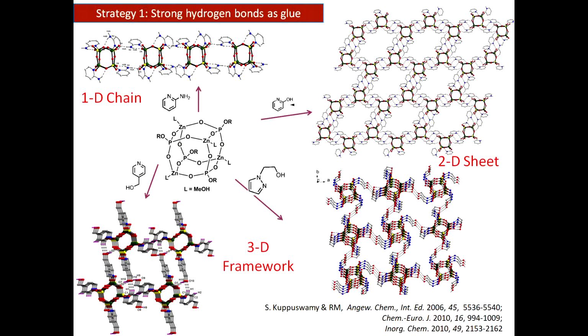To cut a long story short, I think we could only use hydrogen bonds as the linkers. This is probably the first and only example to date of purely hydrogen-bonded metal phosphate zeolitic materials, where instead of using collidine, which I showed in the previous slide, I still use pyridines, but the pyridines are decorated with an additional functional group. It could be a hydroxypyridine or aminopyridine, or a pyridine methanol, pyridine ethanol, or it could even be a pyrazole.